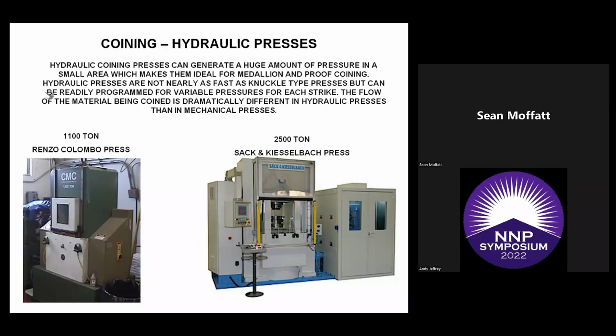So these are really nice and programmable like that. But as you get into higher tonnages, the presses don't really get that much bigger like they do with the mechanical presses. This here is an 1,100 ton Renzo Colombo press, also sold in the U.S. by CMC at the time. This press weighs less than 5,000 pounds, removed with a 5,000-pound forklift. And if you remember, the 1,000-ton knuckle press weighed 10,000 pounds. And this here's a 2,500-ton Sack and Kiesselbach press, and that one there probably weighs close to 20,000 pounds. A pretty good machine. Higher tonnage hydraulic machines are much smaller for the size and the pressure, but you're also giving up your speed. So it depends on what you want to make, which way you want to go.